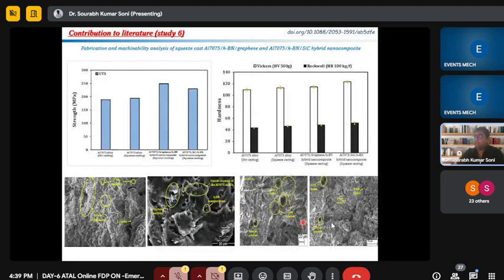This is the optical microscopy of the squeeze cast specimen. See, this is the aluminium 6061 and aluminium 7075 through squeeze casting, no reinforcement. But here, this one is the HBN graphene, and this one is the SiC HBN. So there is significant grain reduction, significant grain refinement. So we can say that as per Hall-Petch theory, there is significant grain refinement, so mechanical properties will increase like that.